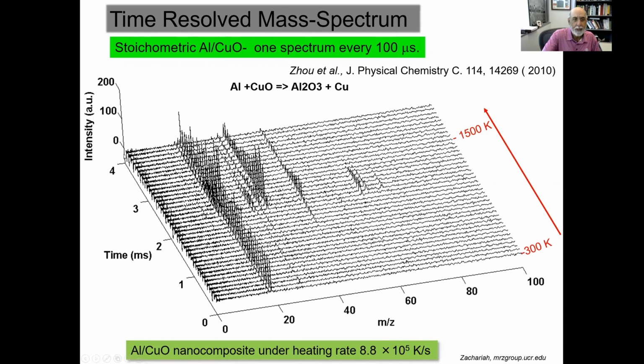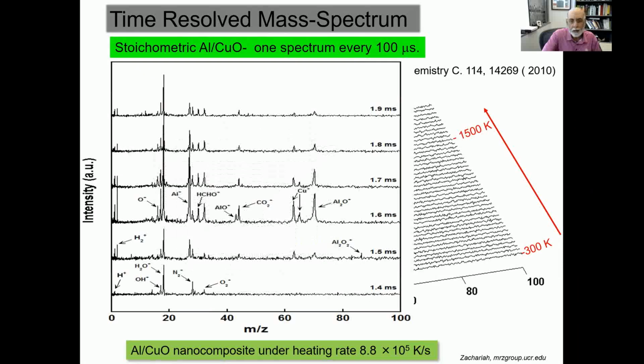So this is what spectra would look like. This is time in milliseconds. This is mass over Z. And the red points to temperature. And so you can see various species come along and be formed and then disappear. And you can dig into what those species are and try to extract information about the trajectory of these condensed phase processes that are going on.